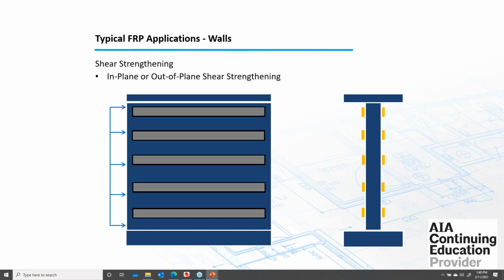There's different requirements as far as the thickness of the wall. So I think it's like 4-inch walls and 6-inch wide walls, you can get away with putting the material on just one side of the wall. If it's 8 inches or wider, then you have to actually put the material on both sides of the wall. That all comes straight from the ACI guidelines. I'm sure probably there's a similar requirement in the CSA as well, as far as which sides you need to place it on. But generally anything 8 inches or wider, which I believe is 200 millimeters, you need material on both sides.